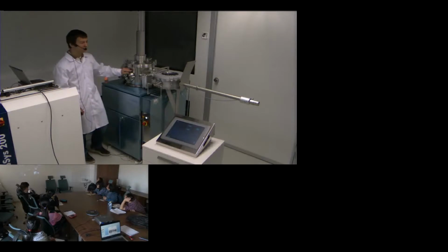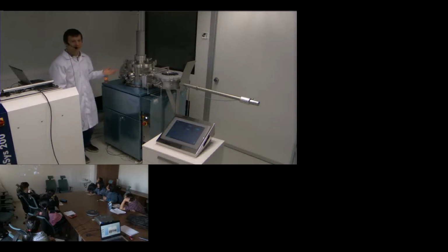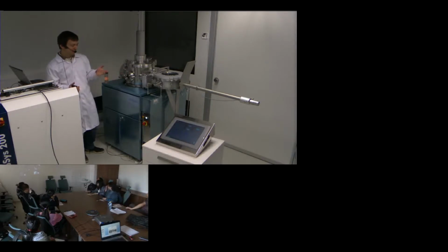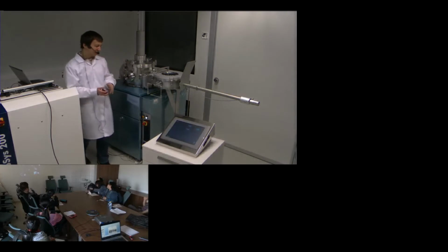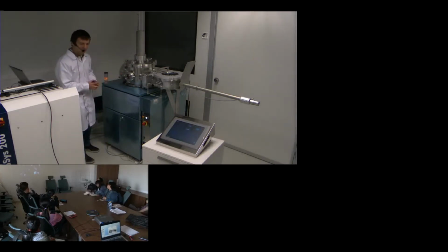What we can do with ALD is deposit single atomic layers of oxides or nitrides of many elements. What is important here is that this deposition takes place from the gas phase. We just expose our sample to a combination of gases which react on the surface, forming an atomic layer. And by repeating this process several times, we can perform growth of the layer, layer by layer, really with atomic precision.